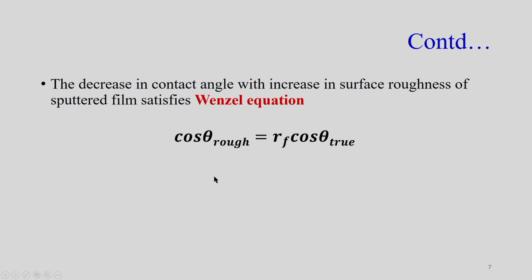Now, we try to relate the surface roughness with the wettability, and we found that it agreed to the Wenzel equation, which says that the contact angle on a rough surface is RF, the roughness factor, into the true contact angle.